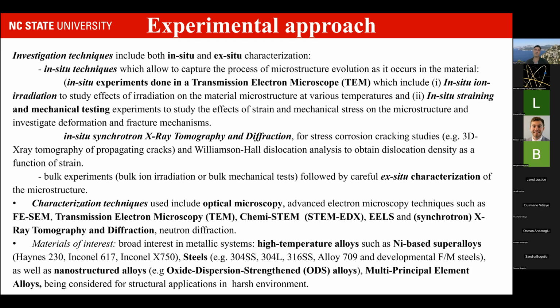That was especially of interest for understanding the mechanical behavior of developmental alloys of interest for DOE. In situ experiments usually involve very small samples, and therefore it's always good, if not necessary, to couple these types of experiments with bulk experiments, whether it's bulk irradiation or bulk mechanical testing, followed by ex situ characterization. That way we can substantiate the effects of having a small sample, the effect of thin foil surfaces, etc.